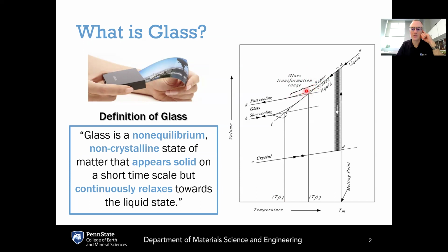It's a gradual freezing-in process, and we are simplifying that by introducing a fictive temperature that says, okay, within that range of temperatures, let's pick one of them, this fictive temperature where these lines intersect, and that is approximately where the supercooled liquid has been frozen into the glassy state.